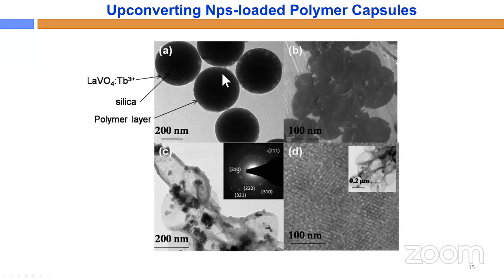Image A shows the lanthanum vanadate coated silica, and the contrast clearly shows that it has the lanthanum vanadate. And figure C is the transmission electron microscope image. The nanoparticles are inside the polymer capsule, from the contrast which we found. And we have done the high resolution transmission electron microscopy that shows that the nanoparticles are highly crystalline. As I mentioned, in this case we need very highly crystalline nanoparticle, then only we will get a very high fluorescence because of the upconversion.